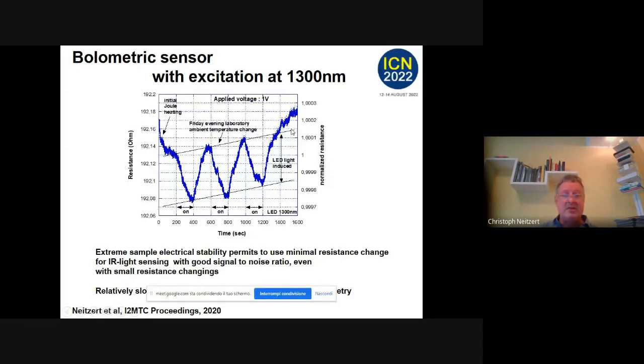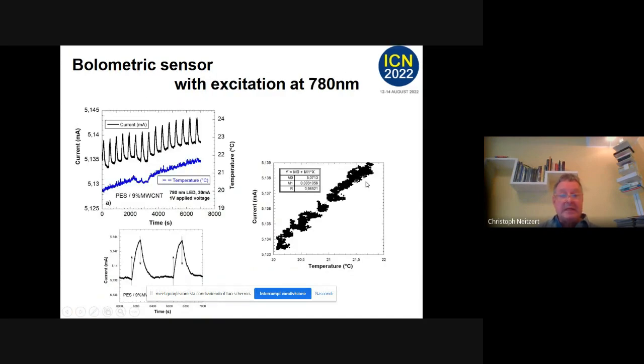Actually, this is the change in the temperature of my laboratory. It was a Friday evening experiment, and they switched off the power, the conditioning system. Now we did the same again, and I show you again. We look for reproducibility. We changed now to 780 nanometers, and we measured at the same time again the temperature.